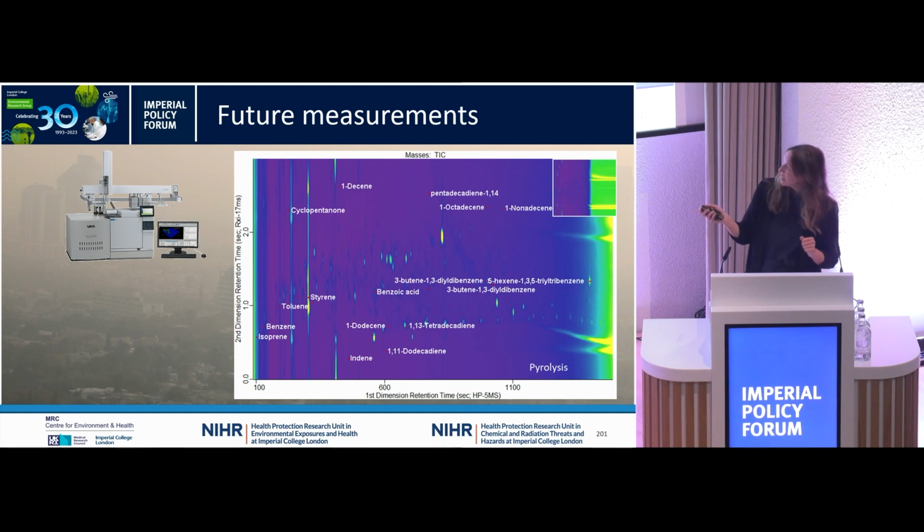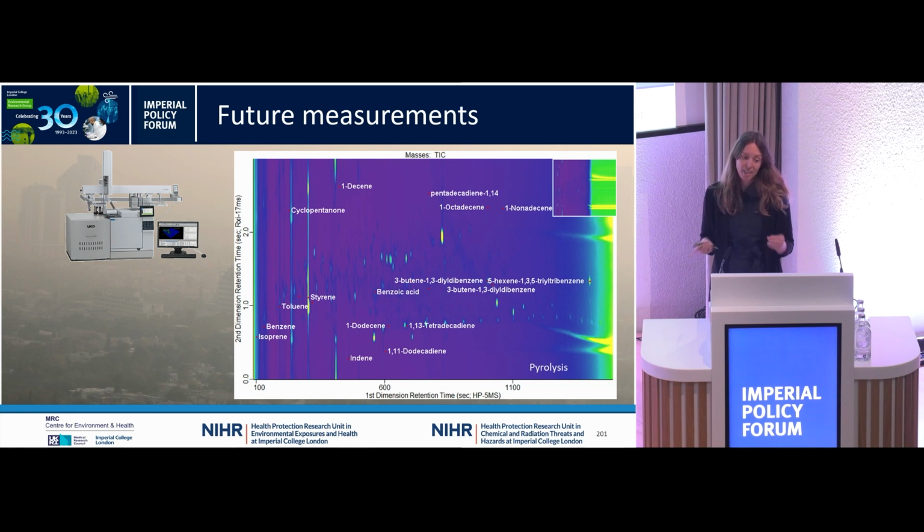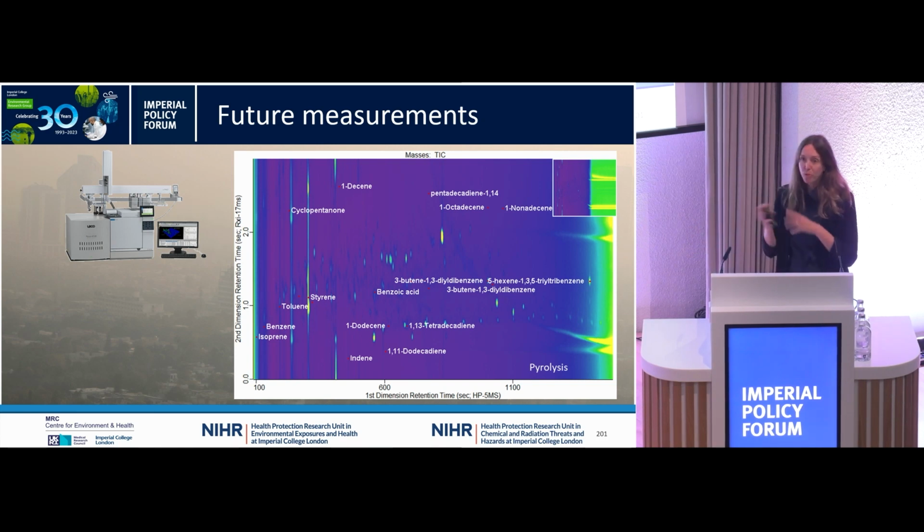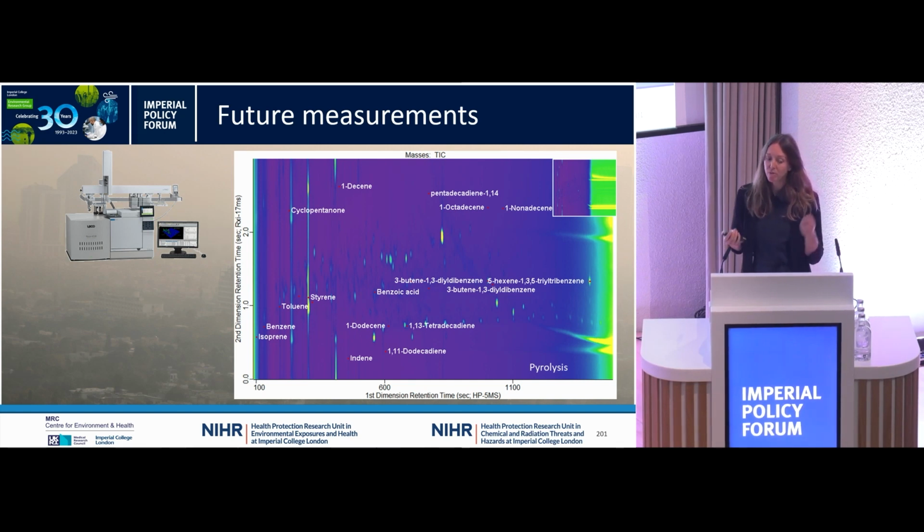But for us specifically in this application, we were interested in whether any microplastic or plastics were present. And so all of these red spots with the labels each relate to a chemical marker of plastics. Some plastics have 3 different markers, some have 4, some have 1. And if all 3 are present, that really qualifies the presence of that plastic in our sample.